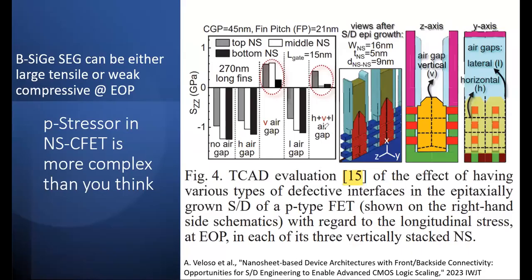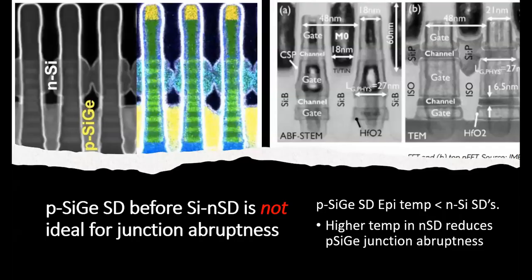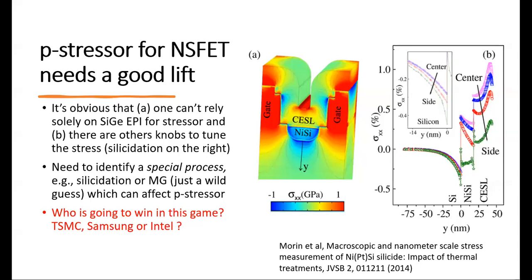So the defect, as we mentioned here, the stress and strain defect will change your strain, could potentially change your strain from compressive to tensile. That's not what you want at all. Or the germanium on the bottom could force you to reduce the temperature of source drain on the top. It's not a good thing, right? You need to activate your source and drain. So all the temperature has been optimized. And if you're restricting their temperature, then you are reducing your activation efficiency. So that's not good. The bottom line is this: one cannot rely solely on SiGe epi for stressor in the nanosheet CFET.